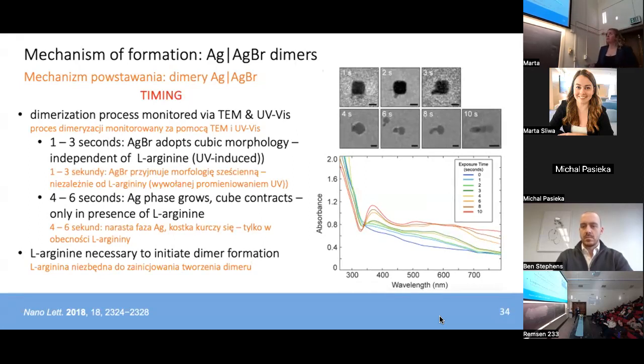So in that first phase, over the first 1 to 3 seconds, the silver bromide host turns from spherical to this cubic silver bromide morphology, and that process is independent of the presence of L-arginine, so it's strictly a UV-induced process. Whether or not we have that molecular reductant there, first 3 seconds, we get a silver bromide cube. 4 to 6 seconds, or that second phase of the growth, the silver phase grows out of one corner of the silver bromide cube, the silver bromide starts to contract and form a sphere, and then we eventually get this 2-phase silver-silver bromide dimer as our product.